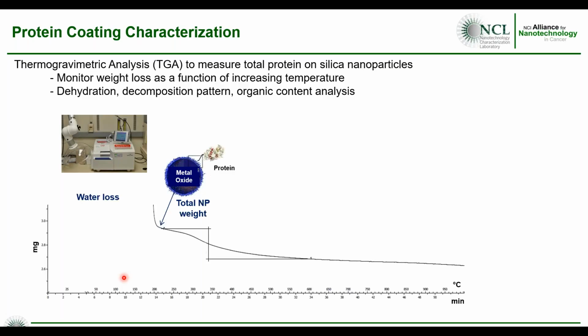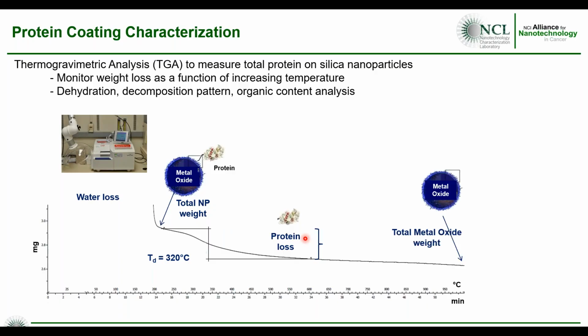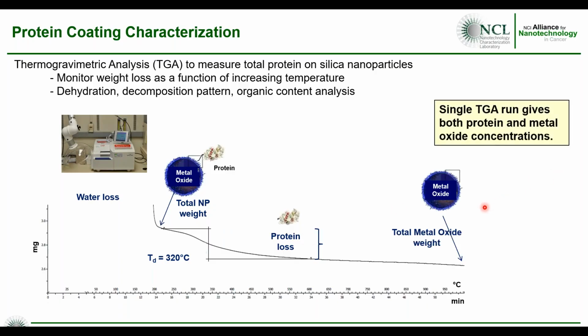So we were looking in this case at a metal oxide with protein coating. We increase the temperature, we burn off this protein coating, and the weight loss corresponds to how much protein is on the sample. And in this case, since you have a metal oxide, you don't burn this off at the end. So the final weight at the end of the run will give you an idea of how much metal oxide you have in the sample. This is useful if you don't have ICP-MS, for example. And a single TGA run gives you both protein and metal oxide concentrations.